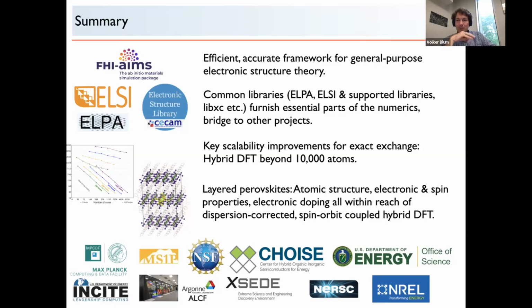somewhere and hope. It turns out that, because of excitons in the systems, getting the fundamental gap in the perovskite is not that easy. But we know for phenethyl ammonium lead iodide, for instance, that we're at the lower end of the alpha parameter, the exact exchange parameter that we should be using. We actually undershoot the band gap in this case by 0.6 electron volts. That's about the largest that I know from databases that have been published. But that's in the range of HSE as it's been published in the literature and its accuracy.